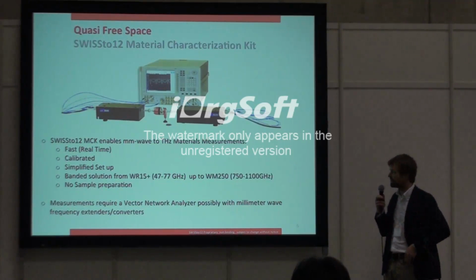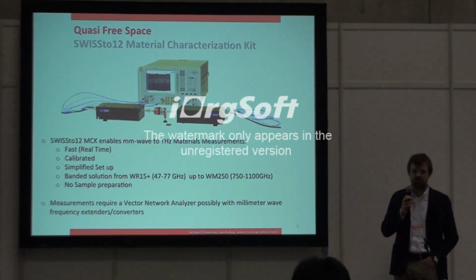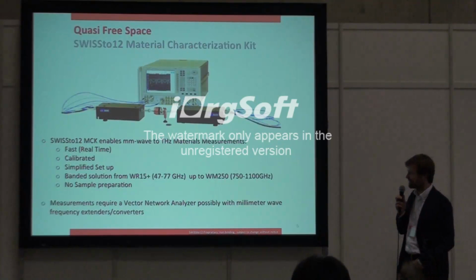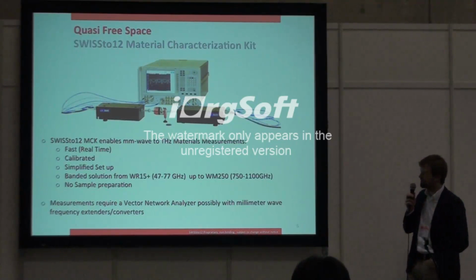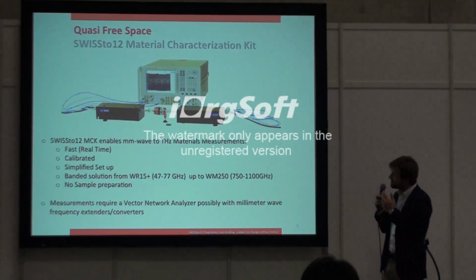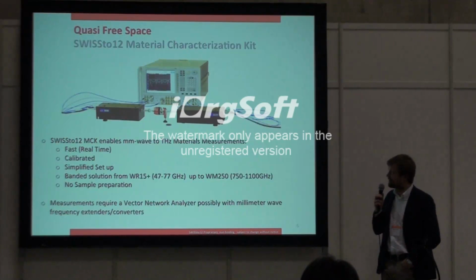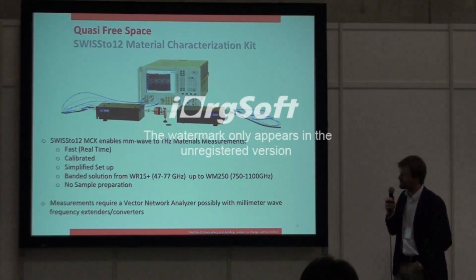So for each frequency band at which you can do measurements, we produce one of those kits. And the objective of this kit is to minimize sample preparation. So we do not require customers to cut their samples into particular shapes to enable the measurement. And the traditional measurement setup comprises a vector network analyzer with some frequency extension modules to bring up the measurement capability to these millimeter waves and terahertz. And then the test fixture to do the measurements. There's a calibration standard provided with the fixture. And we also provide a software that runs the measurement and does the data analysis.